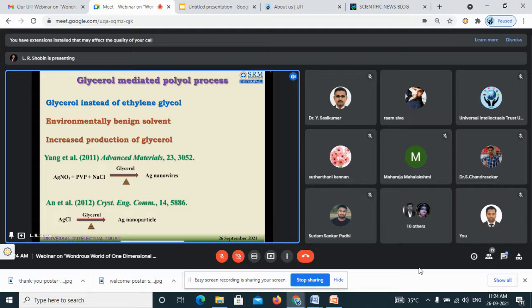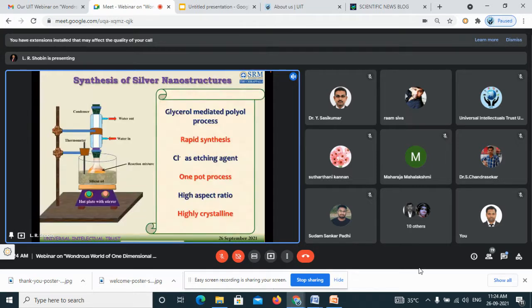They are not able to realize transparent conducting films using their silver nanowire crystals. So I modified the process. I call it the modified polyol process, glycerol-mediated. The process is simple. You can synthesize the wire within 30 to 40 minutes actually. It's a rapid process.